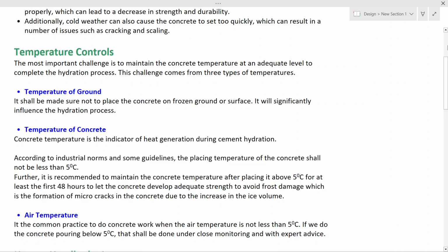Temperature of the concrete. Concrete temperature is an indicator of heat generation during the hydration of the cement. According to industrial norms and some guidelines, the placing temperature of the concrete shall not be less than 5 Celsius. Further, it is recommended to maintain the concrete temperature after the placing.